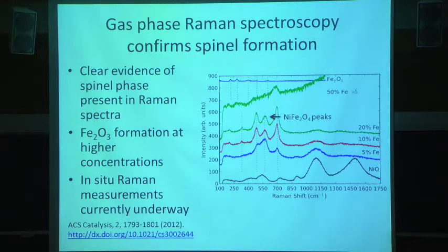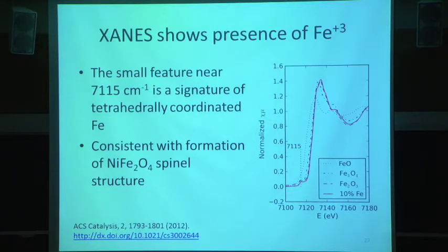So these are ex situ dry powders that we put in the Raman. We can see the iron spinel phase. We're currently working on these in situ measurements. I'll talk about those right at the end. Okay, and finally, if we look in XANES, this little pre-edge feature right here is indicative of tetrahedrally coordinated iron, and that is exactly what would be in the spinel phase. So we're reasonably sure we have the spinel phase in all of the samples that show very high activity. And when you start getting the Fe2O3, you get substantially lower activity in the electrocatalyst.